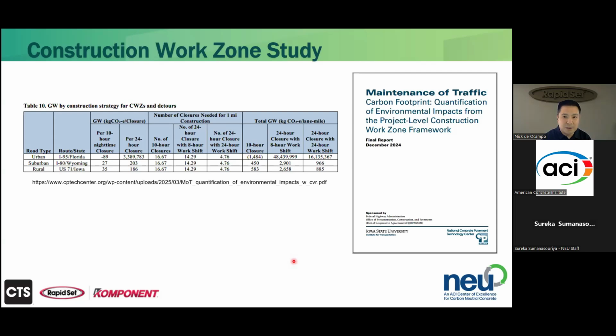So it is just simply a massive amount of CO2 emissions saved if you can avoid all of that traffic congestion in the urban environment by utilizing an overnight, 10-hour closure. I should note that the suburban and rural locales also showed an emission savings, roughly 2,000, 3,000, 2,600 kilograms of CO2 per lane mile. But that's nothing compared to the 48 million that they look at.